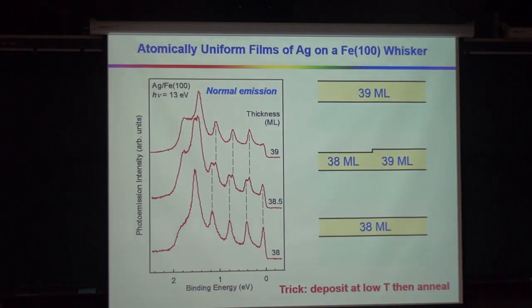So this is actually very important to demonstrate that at 38 layers, we have no 39. Okay, there's no peak. And then we can also show there's no 37. So only 38, exactly 38. Yeah. So we were the first ones in the world to demonstrate this is possible. And most people make films where, when you say 38, you could have 30 all the way to 50 in your distribution. But we can make this one.